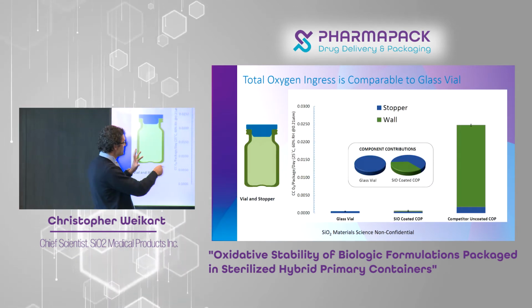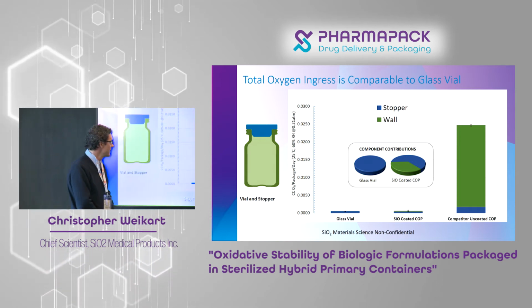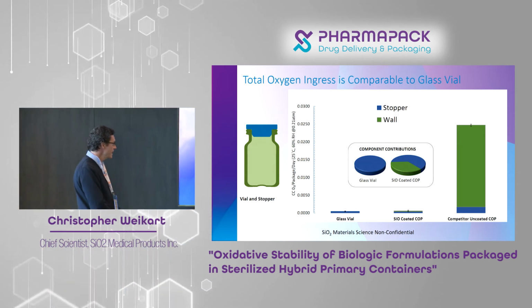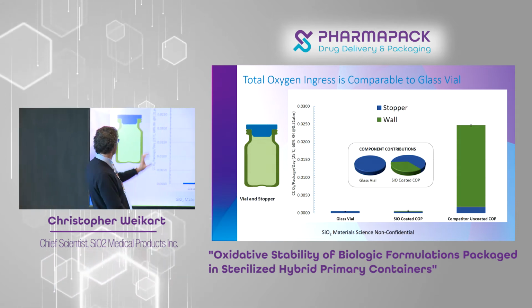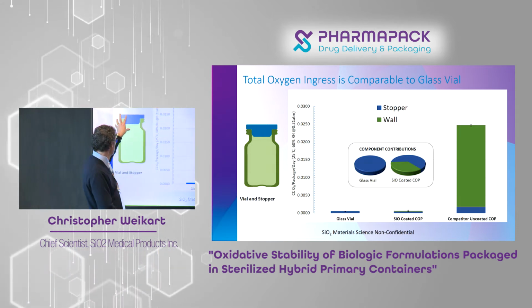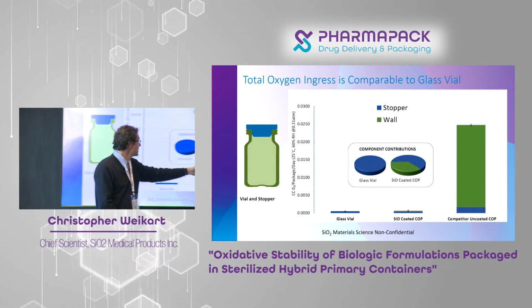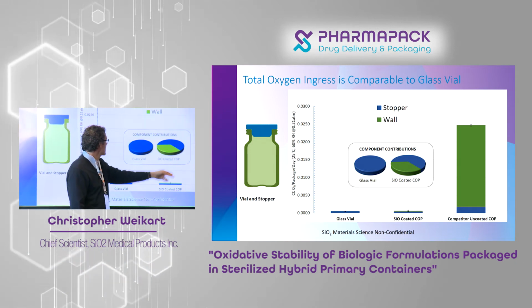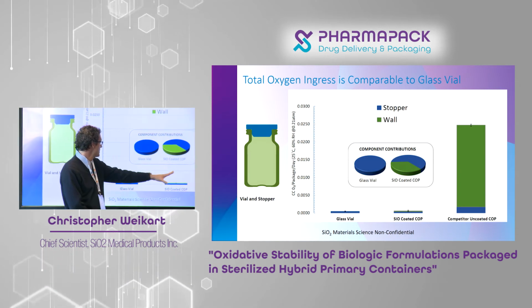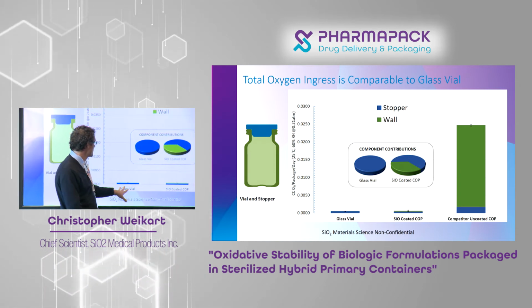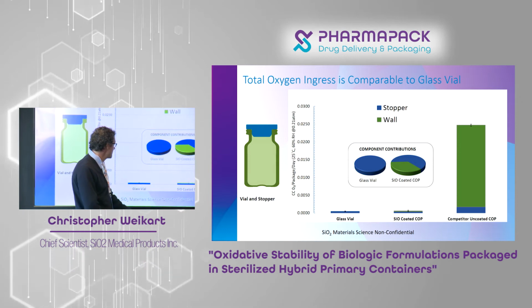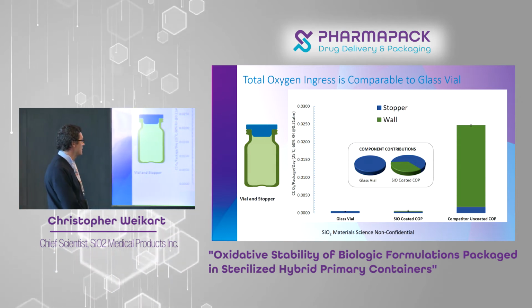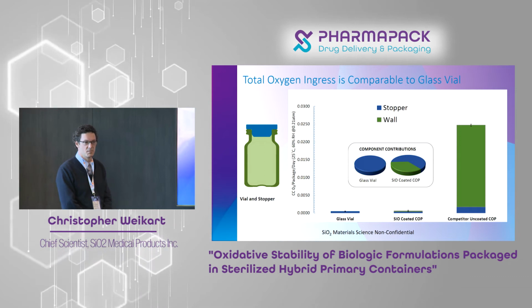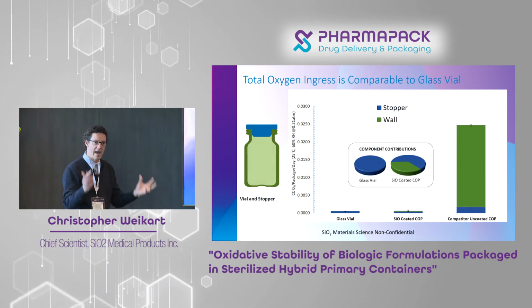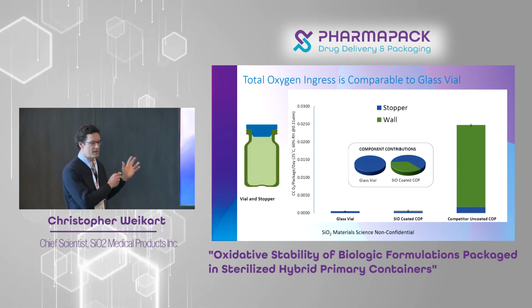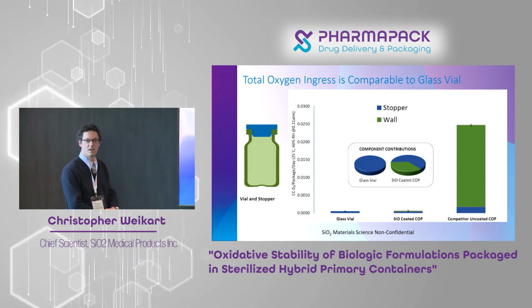So this is just a little bit of a perspective on how you compare it to an uncoated container and to a glass container. And then what's the contribution of oxygen coming in through the closure and through the wall? So here's an uncoated container. You can see obviously a lot coming through the wall versus the stopper. And then here's us compared to a glass vial. There's a slight difference, obviously, in the permeability through the wall, but by comparison, it's very, very similar in total, if you look at the entire package, including the closure. I've got examples of syringes, the same sort of relationship exists.